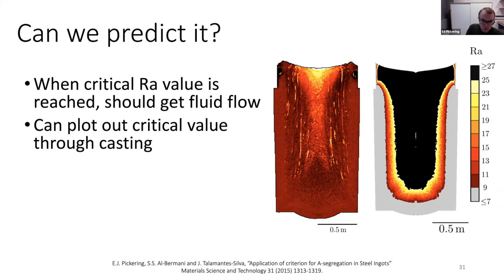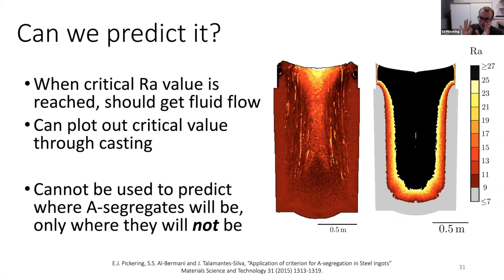And there's another point on this slide. Oh, there we go. So the key thing, not that this is a bit of a detail now, is that you can't actually use the Rayleigh criterion to tell you where A-segregates will be, only where the good material is. Because you can see in the middle here where there definitely should be lots of fluid flow according to the Rayleigh number, there are actually no channels, and this is because other phenomena are taking place. But essentially it gives you an indication as to where you first start to have a lot of this interdendritic fluid flow taking place, and hence forming channels.